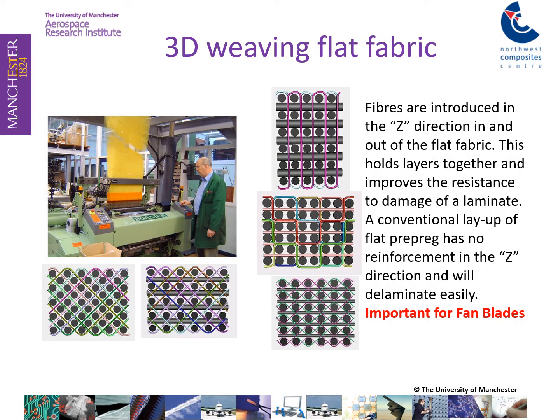3D weaving, introducing fibers in the through thickness direction, in the Z direction, enables us to prevent those delaminations. And here again, you need those mathematical models to optimize the fiber architecture, which still is going to produce a light, stiff, strong, and at the same time damage-tolerant construction where delaminations are harder to happen, and when they do happen, they do not propagate.